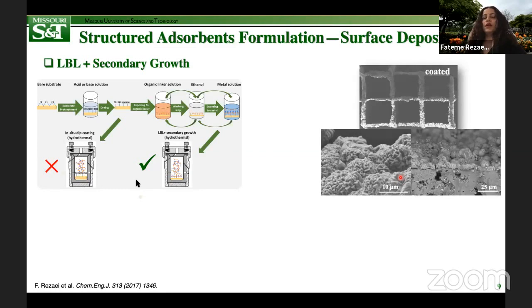All right. In one of our previous works, we employed different coating procedures to deposit MOF films onto a cordierite substrate for use in CO2 N2 separation. Although the simplest coating techniques, which were dip coating and spin coating, have been successful in depositing zeolites on the same substrate, they failed to grow MOFs in our study.